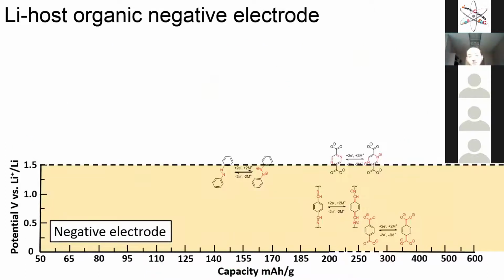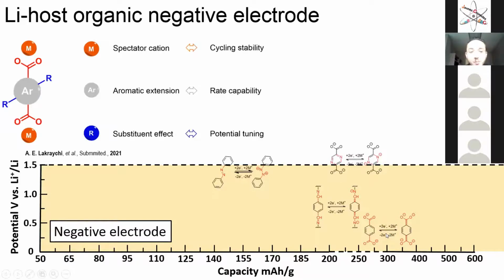So for the anode material here below, I'm showing you the different classes of organic electrode materials. The most promising one is the carboxylate here below, because it provides a low potential and high capacity. And if you take the general molecular structure of this, you have the carboxylate that you cannot change. Then you have the spectator metal cation, you have the aromatic, and you have the substitution that you can put in the aromatic. So these 3 parameters, you can play with them, you can change.